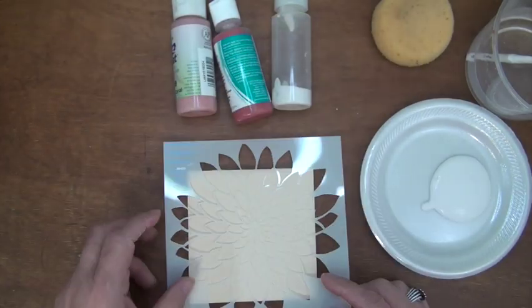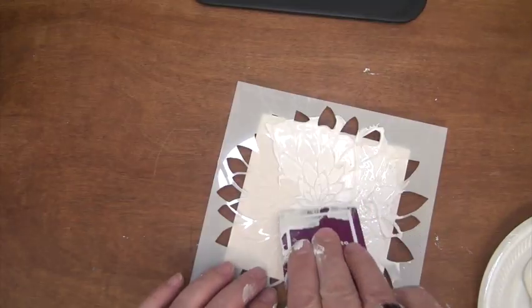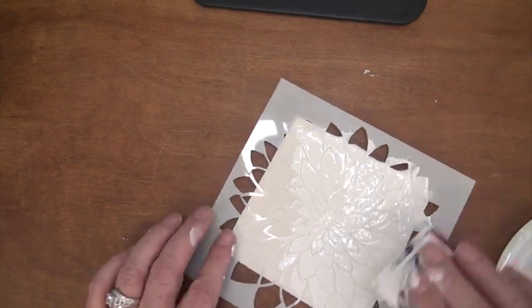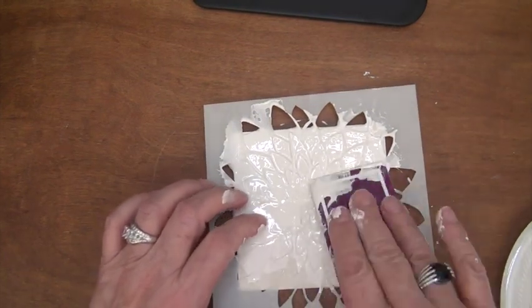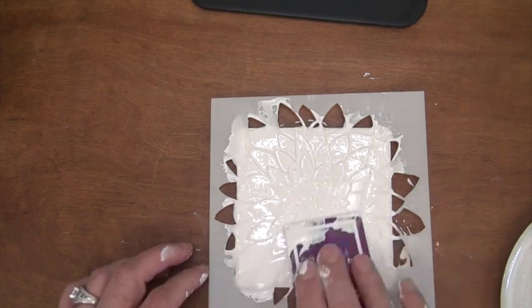You can also use stencils to create dimensional shapes using Snowfall. A tip when using a stencil is to either base coat it with some glaze and apply the stencil into the damp glaze, or wet the bisque so that the stencil lays down flatter. That way the Snowfall doesn't leak under or seep under the stencil.